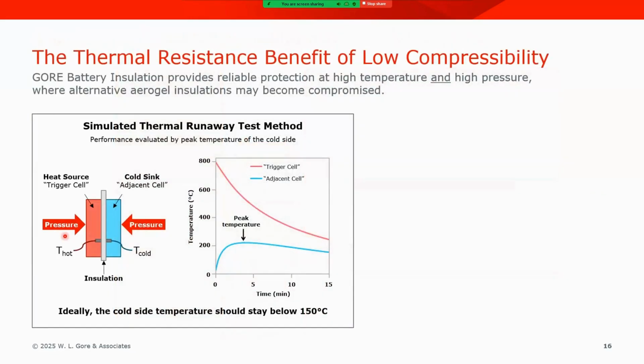So in our experiment, we've done basically a modified hot side, cold side test. On one side, we have a heat source, which we refer to as the trigger cell, and we're going to heat this to 800 degrees Celsius. We're then going to rapidly squeeze a layer of thermal barrier candidate, whether it be the GORE battery insulation or an alternative material, between the hot side, the trigger cell, and a cold side, the adjacent cell. And that cold side is initially maintained at ambient temperature.